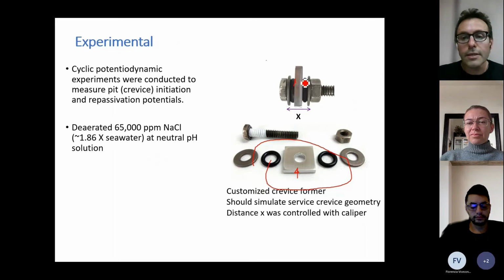And here you have the crevice. Then you have a nut, which is tightened with a bolt here. And if we are careful and measure this distance, and it's always the same, then you have the same severity of the crevice each time and again, right? And with that, we went on to study the effect of this crevice when we expose this material to deaerated and chloride-concentrated seawater, a neutral pH solution, which simulates the service condition, right?